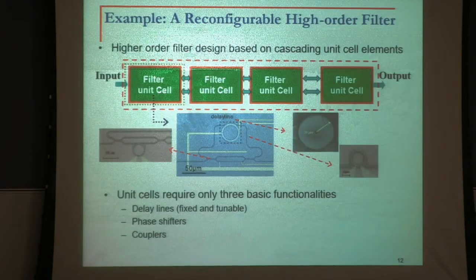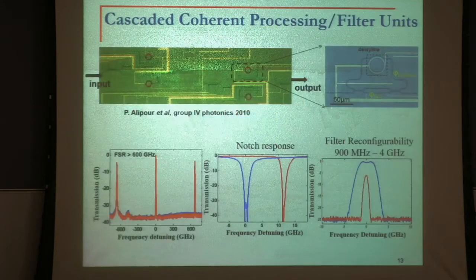This is the example that we did for making a reconfigurable filter by changing the index of refraction of silicon. In this structure, we have a unit cell that's an order 1 or order 2 filter, and then we just repeat that. By repeating it, the same way you multiply polynomials, you increase the degree of the filter, which is identified by the number of poles in the transfer function, and of course the number of zeros. That's the technology we developed for DARPA, and that's the actual micrograph of that. We have 4 resonators. This is an order 2, so that's order 4.